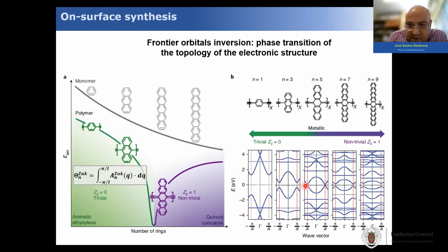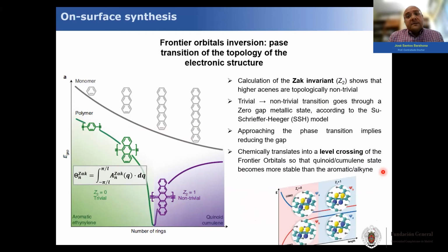So zero gap means that the gap between the HOMO and the LUMO becomes zero, which is the case of the pentacene one. Then as we go further into the non-trivial range, this gap starts to slowly broaden again. In chemical terms, this translates as the level crossing I showed you in the previous slides, where the LUMO of the trivial one becomes the HOMO of the non-trivial, and the HOMO of the trivial becomes the LUMO of the non-trivial.